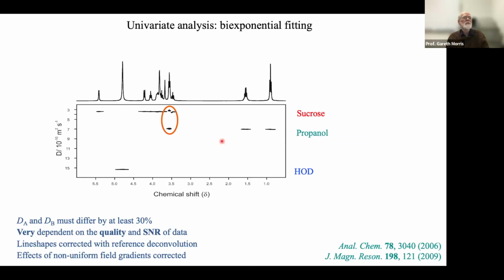These experimental data came from a probe with good dynamic performance, but fairly poor uniformity. The gradient's about 20% weaker at the edges of the sample than in the middle. That's not uncommon, even in modern probes. Do a bi-exponential fit of those data, and you get every peak doubled. So what's happened here is that we have calibrated the gradients, we've measured the variation in gradient position, and we've adjusted the Stejskal-Tanner equation to allow for that. It sounds complicated. You do the calibration once, that works out a set of coefficients for a power series, you store them, and then it's just standard from then on in. But if you're going to try to disentangle overlapping exponentials, you need to make sure they really are exponential. Because if your gradient coil is imperfect, they won't be perfectly exponential.